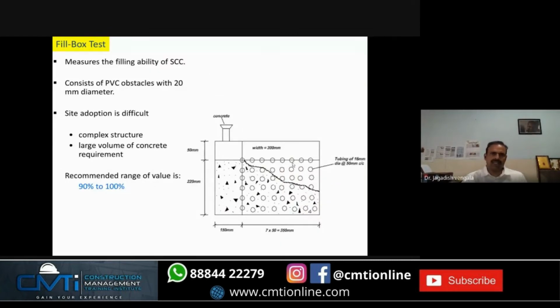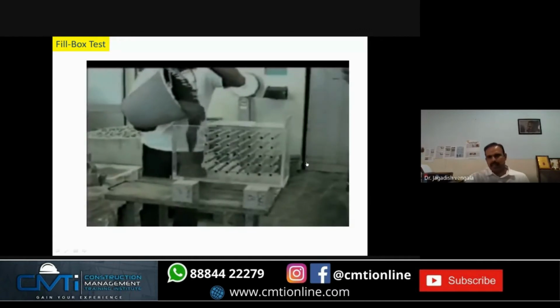There is also the fill box test. Initially, when we started, like in 2001, we actually fabricated one fill box and did the experiments. So here also there is a complex structure. We have the fill box with obstacles of 20 mm dia, and then you pour the concrete on one side, and it has to flow to the other end. You measure the filling area. The filling area should be 90 to 100%. There should not be any gap. That means it has to completely fill. So you can see here the experiment.